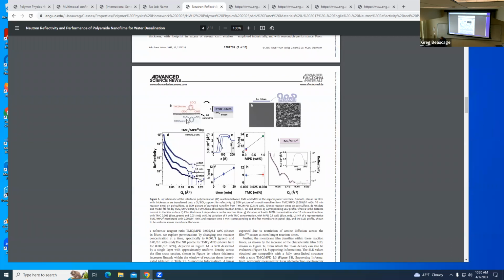And then basically he's using an aromatic to make it kind of stiffer. Anyway, it's basically the same thing as the nylon rope trick, except at a surface, and he doesn't pull the rope out, he just leaves it there. So it's a 100 nanometer rope that's sitting at the surface between the water and the hexane. Then he does reflectivity off that, shoots a neutron beam and an X-ray beam off that. From that, he can get the profile.